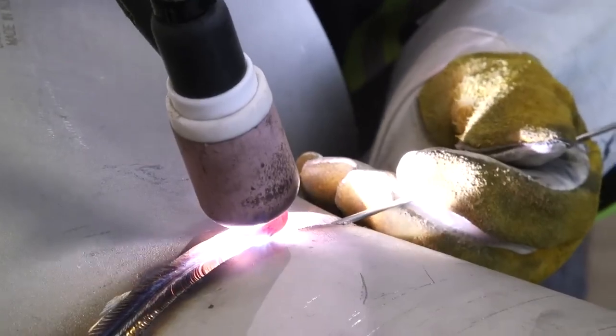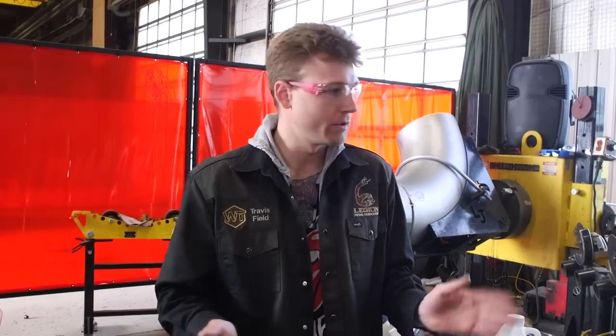If you get a really terrible purge, especially on nickel alloys, when you're beyond 100 parts per million, you'll see little pepper flakes. You'll see kind of a skin floating on the weld puddle. It gets to a point where the oxygen inside the pipe is so bad that your bevels will start dissolving in on themselves, and it's just going to be a terrible purge. So on this duplex, we're striving for essentially less than 25 parts per million, 30, 40 around there, light straw color. That's acceptable on the duplex here for this client.